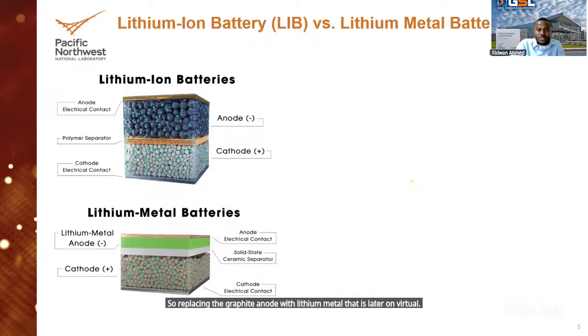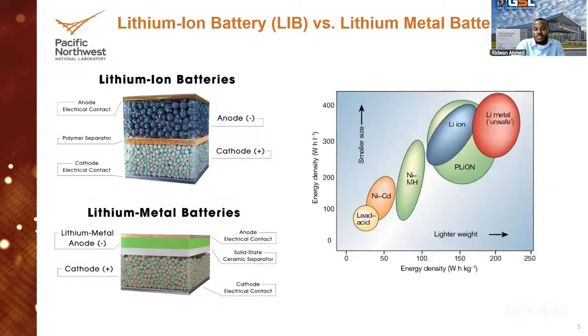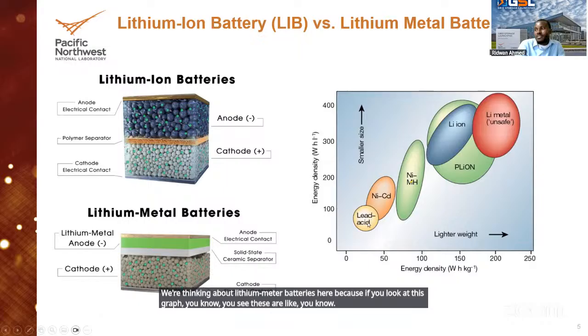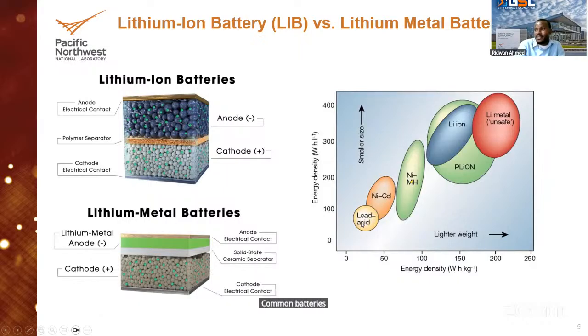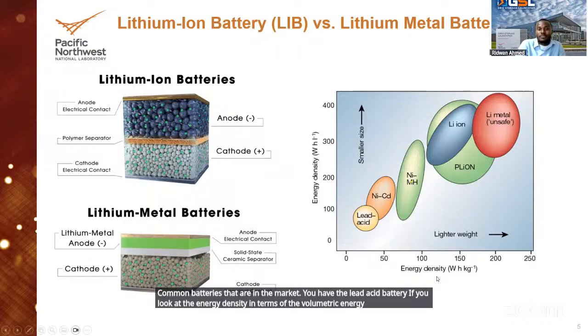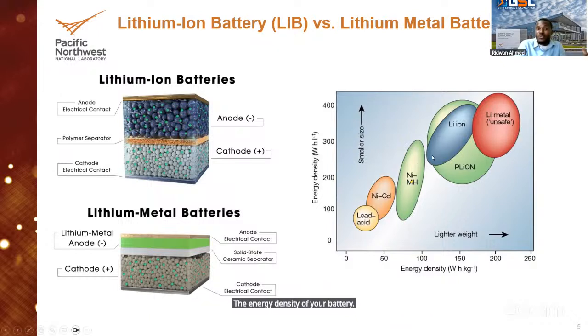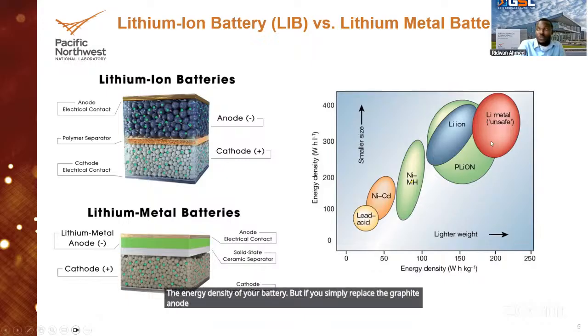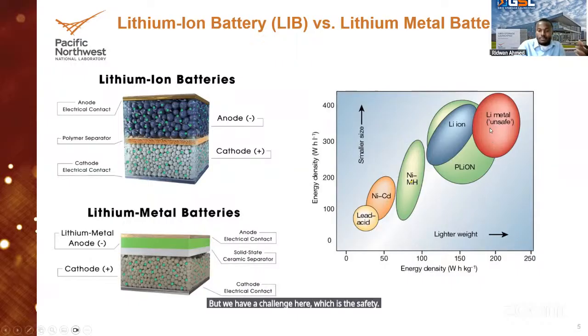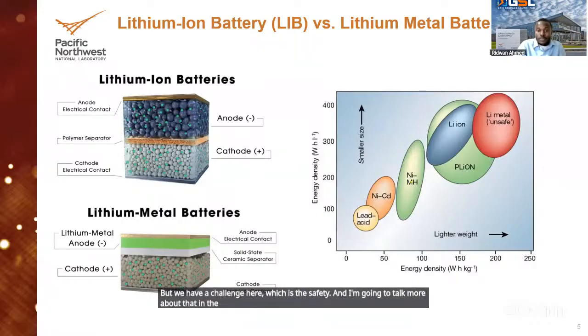Why are we talking about lithium metal batteries? We're talking about them here because if you look at this graph, you see common batteries that are in the market. You have the lead acid battery. If you look at the energy density, in terms of volumetric energy density and gravimetric energy density, you can see that as you move from lead acid to lithium ion, you can significantly increase the energy density of your battery. But if you simply replace the graphite anode with lithium metal anode, you can increase the energy density even further. But we have a challenge here, which is safety. And I'm going to talk more about that in the subsequent slides.